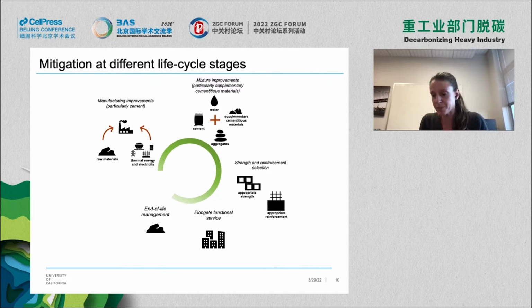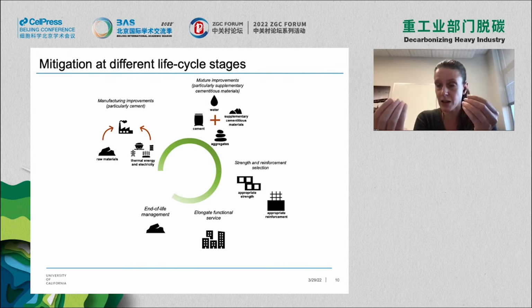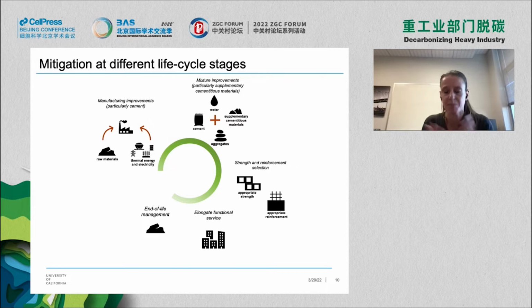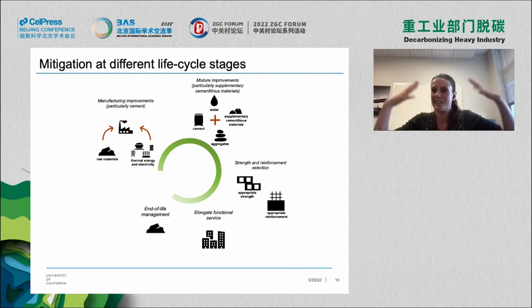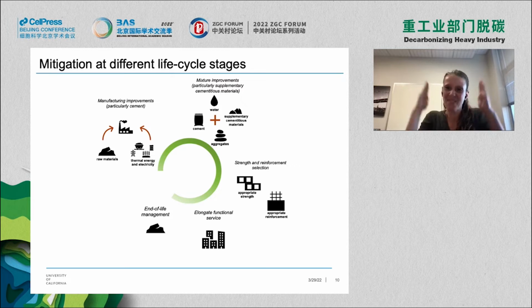Basically, what ends up happening is that our concrete, the cement that has already hydrated within this material, can interact with atmospheric carbon dioxide if there's enough moisture present, if there's enough exposure to the carbon dioxide, basically under the right environmental conditions. Now, while we're using our concrete, not a heck of a lot of this carbonation occurs because in reality, a lot of our concrete is in this bulk area and very little is the external surface that can get exposed to atmospheric carbon dioxide and facilitate this carbon mineralization process. However, at the end of life, we can knock down our buildings, crush them, get a really high surface area to volume ratio, and potentially facilitate a faster carbonation process occurring.